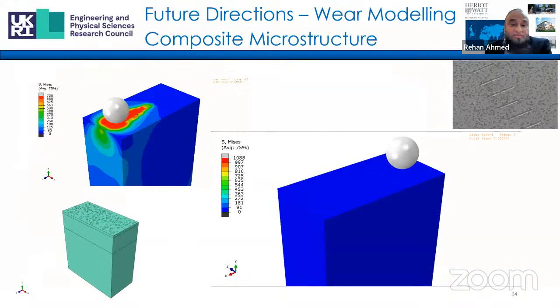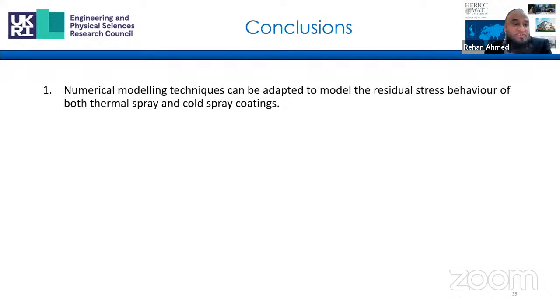And this approach can be coupled with a wear rate numerical model to improve the accuracy of the sliding wear results. And the model can also integrate the residual stress profile during the wear process, as indicated earlier on. So we can couple all of these things together. So this concludes my presentation.